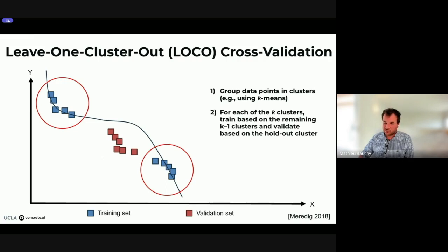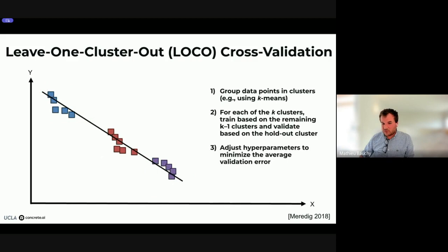And so when we do that, we find that on average, this is going to yield a much simpler model, and models that tend to be more linear in nature and can extrapolate better outside of the range. They are really trained to extrapolate, trained to learn from one cluster and extrapolate to the next cluster. So those types of models tend to be much better to make some reasonable extrapolation outside of the range of the training set that they are trained on.